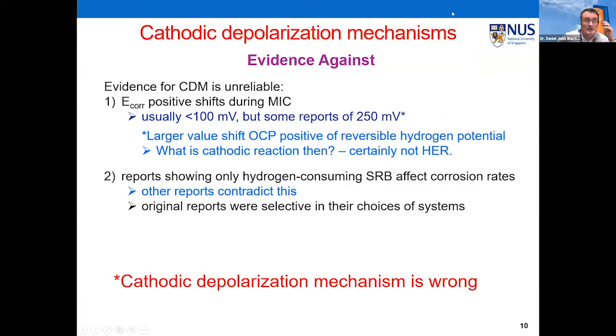Another piece of evidence against the cathodic depolarization mechanism is in the ennoblement itself. We do see ennoblement. Typically it's less than 100 millivolts, but some people report quite large ennoblement, around 250 millivolts. The problem with large ennoblement is that it shifts the open circuit potential positive of the reversible hydrogen potential. So what is the cathodic reaction then? It no longer can be hydrogen evolution, so it can't involve those bugs removing hydrogen from the surface. They cannot shift the open circuit potential positive of the reversible hydrogen potential.